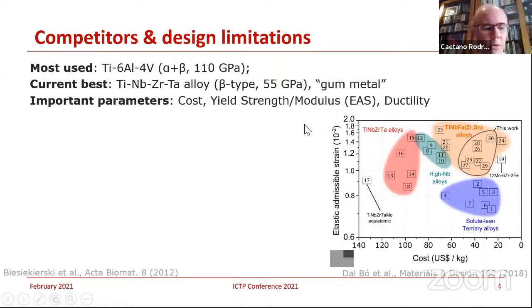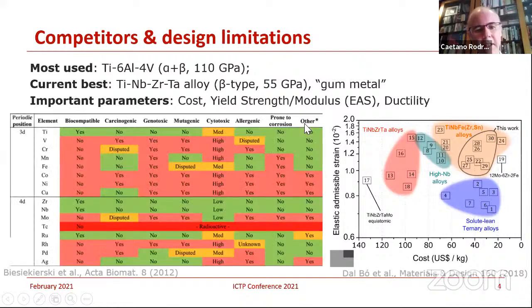Now, the first thing you have to do is look at the periodic table for bioimplants. Basically here you have the metallic systems, these are the elements. You look at their biocompatibility, and there are several other properties to consider. In this particular case, you search only for the green ones, where you could avoid any problem with biocompatibility. That leaves titanium, zirconium, and niobium. Of course, you also have ruthenium, but ruthenium is better used for catalysis, and it also has a very high cost.